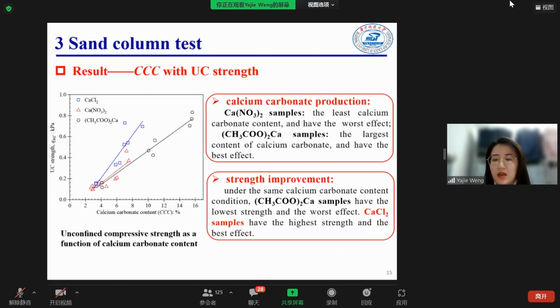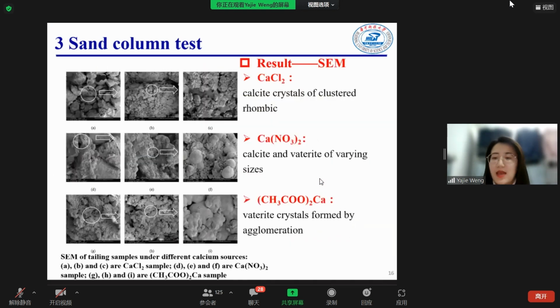The XRD results of the previous solution test have shown calcium chloride has more calcite and its crystallinity is better than that of vaterite. So it shows good cementing effects on the micro level. SEM shows the cementing products of the calcium chloride samples are calcite crystals with clusters of rhombic shape. Calcium nitrate sample products are calcite and vaterite of different sizes. Calcium acetate sample products are vaterite crystals.